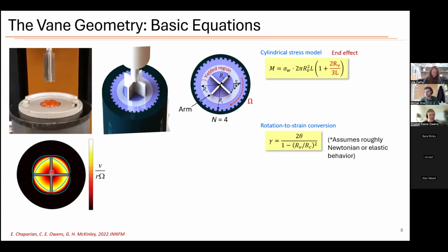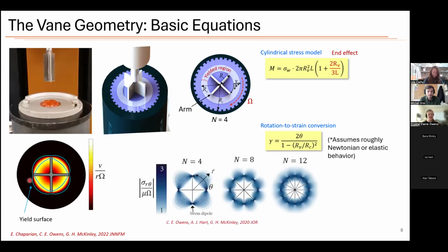But now looking more closely at the 4-arm vane, we participated in some studies doing a simulation of what happens when this actually rotates. This is highlighting where the yield surfaces are on the material, where people might assume that they're circular. If you look at a cross-section, in reality, we find that they have a very lobed-like structure. This is because if you do careful stress calculations, if you have a 4-arm vane, then you're going to have points of stress singularity at each of these as it rotates concentrically inside the cup. But we found in a previous study that as you increase the number of arms, this does smooth out considerably.